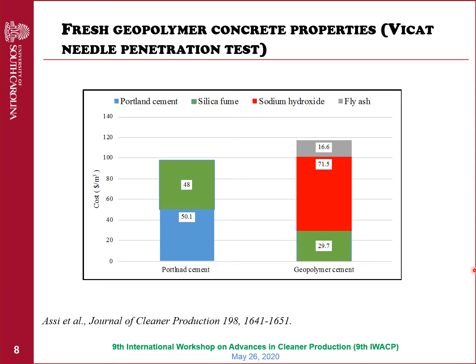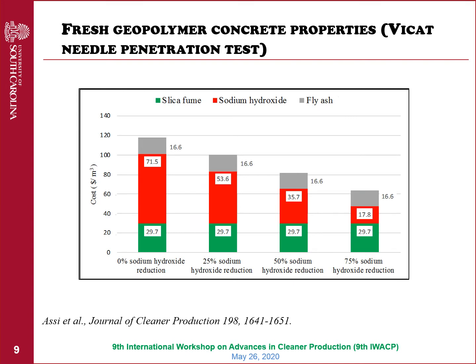The second thing that we checked is the cost, and we found the cost of our concrete is much higher than Portland cement concrete, which really hinders the penetration of this concrete in the market. Most customers focus on the cost and then the properties. So we introduced a new mix design by reducing the ratio of sodium hydroxide, which is the main reason for this high cost, and we reduced the cost by 40%.